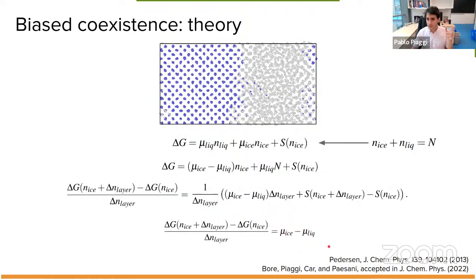This is similar to the interface pinning method introduced by Ulf Pedersen. And what I'm describing here is a generalization, because in the case of interface pinning, they put a single umbrella potential that fixes the location of the interface. What we will try to do is something slightly more complicated, that is building a bias potential that creates reversibly a full layer such that we can neglect this surface term. But in order to do that, we'll have to create a bias potential adaptively, for instance, using metadynamics or some other technique.